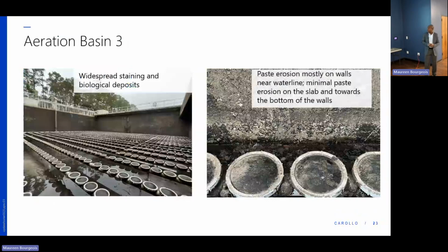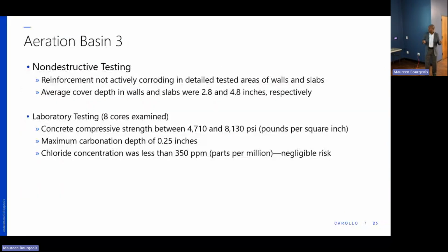So for aeration basin number 3, what are we recommending? We did all our non-destructive testing with all our equipment, and it reveals that the reinforcement is not actively corroding in the areas of the walls and slabs that we tested. The cover depths from our equipment testing also show that at the walls, we have about 2.8 inches of clear cover. We talked about having a minimum of 2 inches from the face of the rebar to the face of the concrete. We have 2.8, so that's good news. And then at the slabs, we have 4.8, so that's also good news.